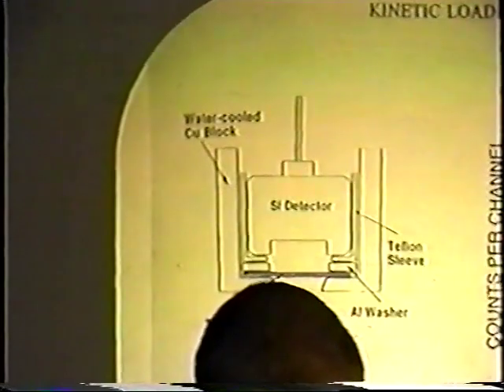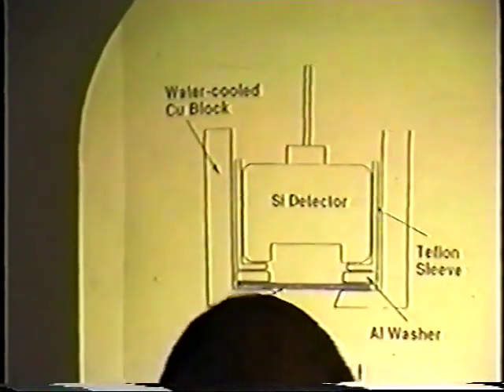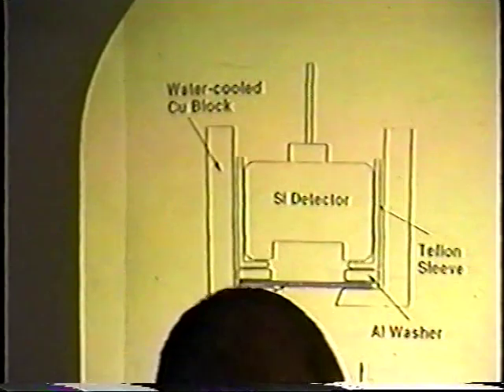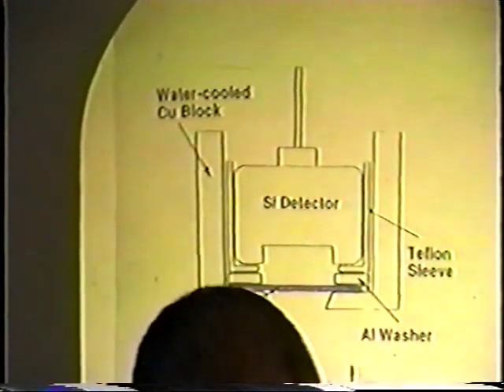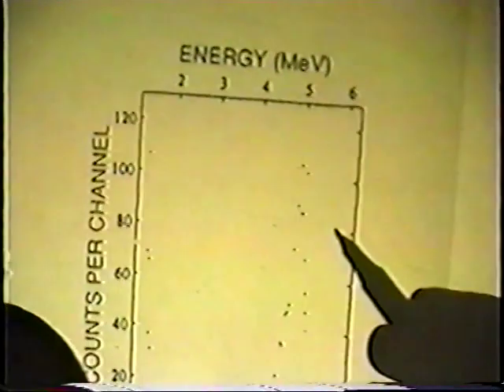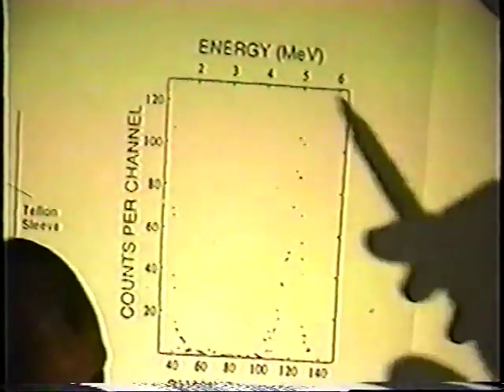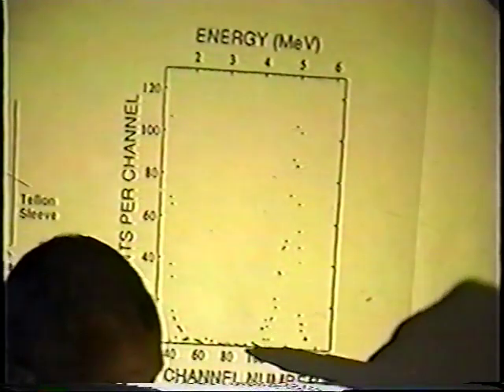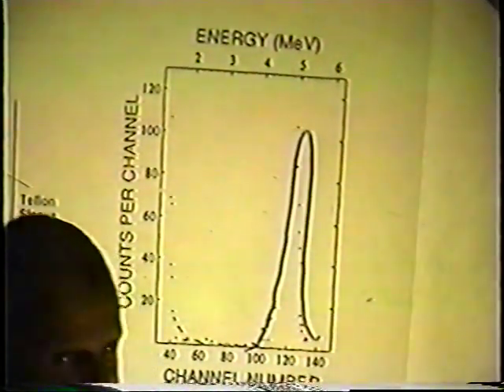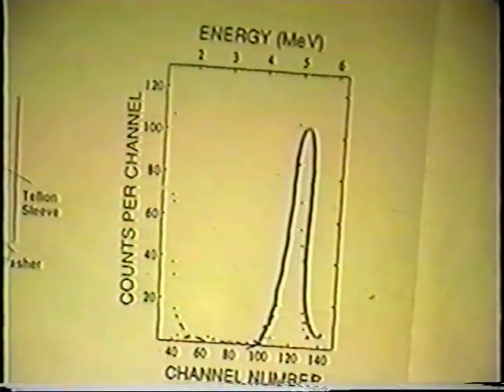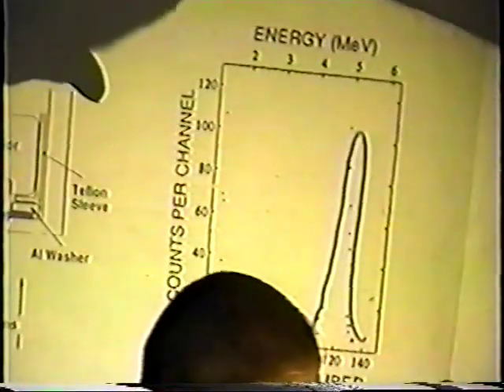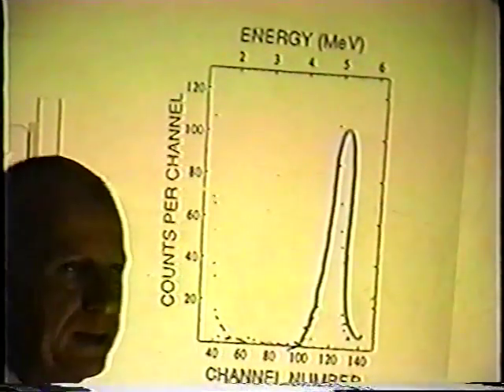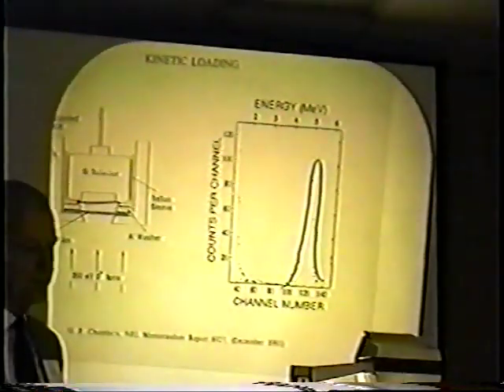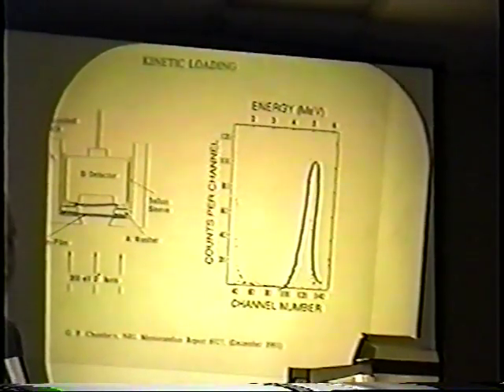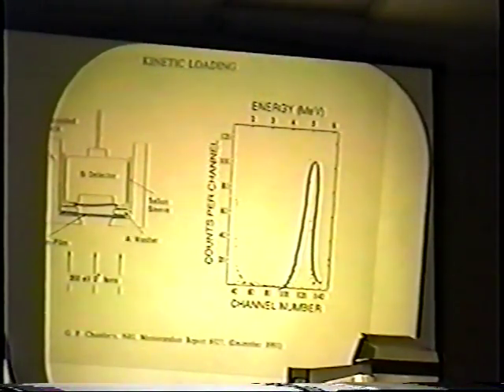The experiment was to load a titanium foil here with 350 eV deuterons and to look immediately behind it with an energy-sensitive particle detector. And what we saw is an example that's indicated on the right. You have energy, MeV on the top, and counts per channel here, and we saw a very, very strong peak here around 5 MeV. Now, we got this a few times. We interspersed absorbers there and saw the peak attenuated and shift. We changed the conditions on the detector. We did a lot of experiments, and it looked as though it was a triton, a 5 MeV triton.